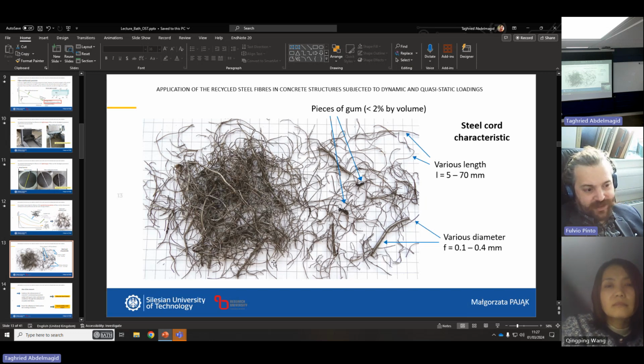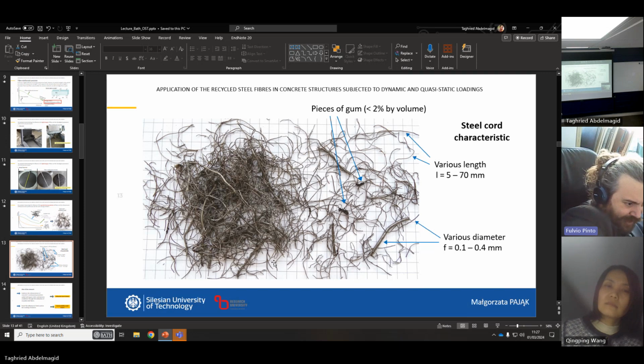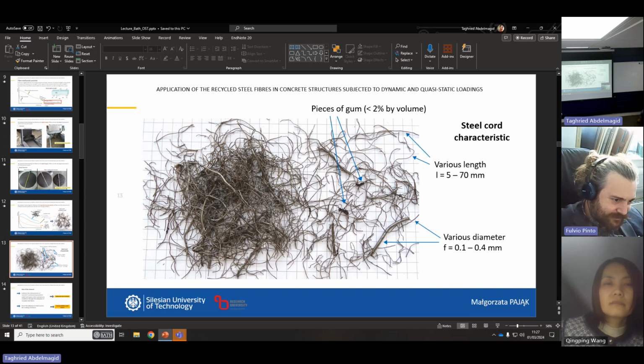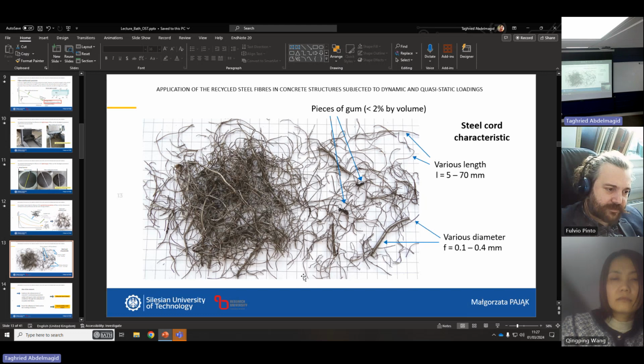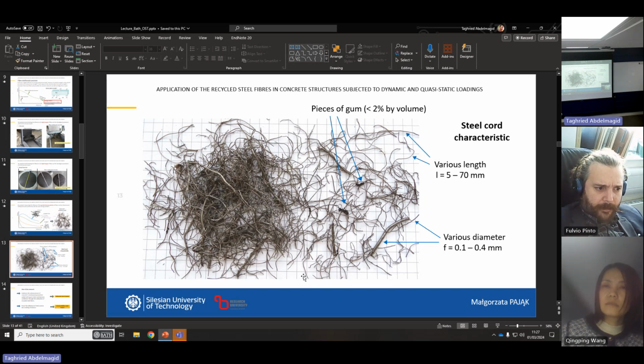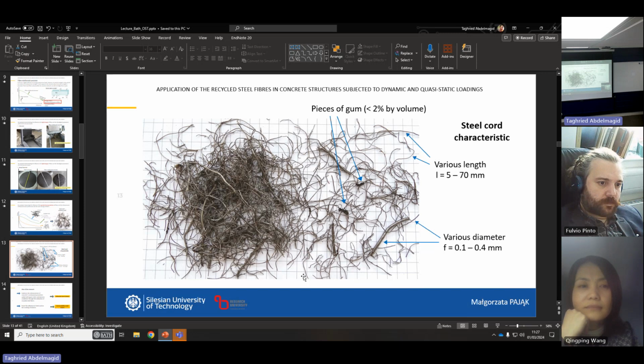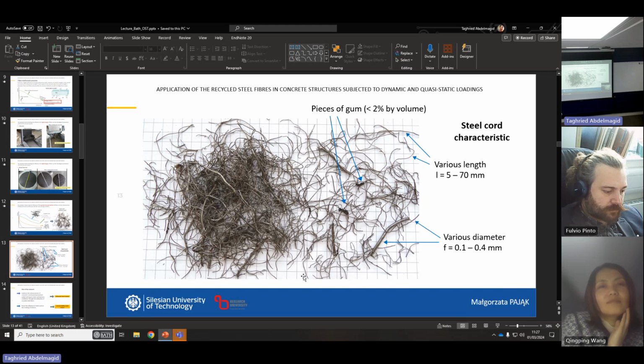Yeah, and that would definitely create a stress intensification point. Yes, crack generation. You can see one on the left, I think. Here is something. So it works like this, but generally I'm surprised that we achieved very small scatter between the results for these mixes, because the bigger the fiber I tested, the bigger the scatter. For example, for the biggest hooked fibers, the performance was very high. The hardening phase was very high, a two-times increase of the flexural and tensile strength. However, that was in one specimen, and in the second specimen it was like plain concrete because the fibers were not where they should be.